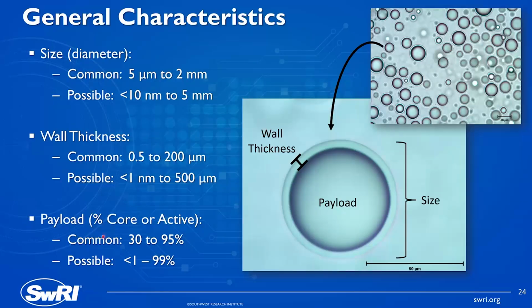And then finally, payload. So this is the amount of active material within your capsule. So the amount of water in the water balloon, the amount of chocolate in the M&M, how much can I stuff in? The amount of blueberries in your blueberry muffin. So with atomization, spray drying, that I'll talk about here shortly, 30 to 40% is more common and maybe on the lower end. You're not going to get much above 50% with a matrix particle. So think about if I try and stuff 50% blueberries into my blueberry muffin. That muffin becomes less effective at protecting those blueberries. For core shell capsules, 95% is a rough high end.